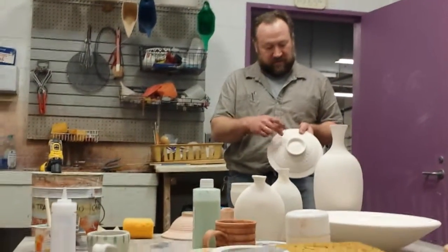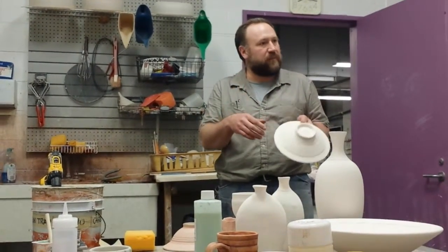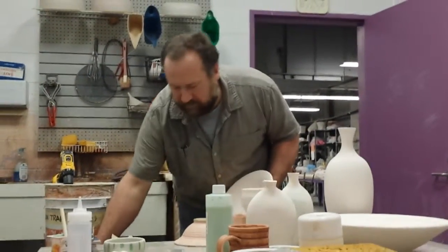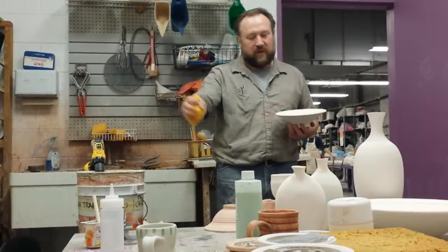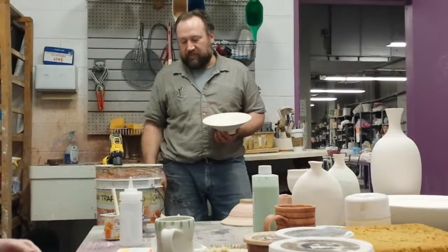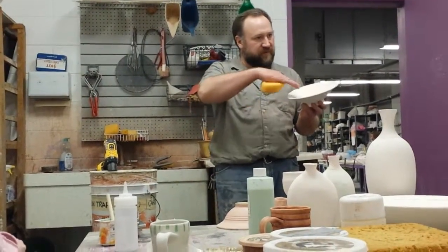It will show texture because of the different layers — the chattering on the bottom of a bowl will show more definition because the glaze will settle into the deeper recesses and sort of peel away from the higher points. If you want a really smooth coat, you can wait a little bit for the bubbles — but know that the materials in suspension are settling. The best way to deal with it is to let it dry and then take your finger and rub slightly over the surface to fill those little pockmarks.